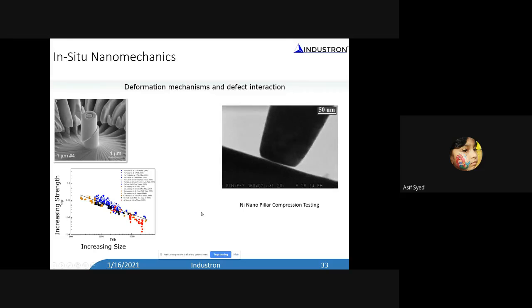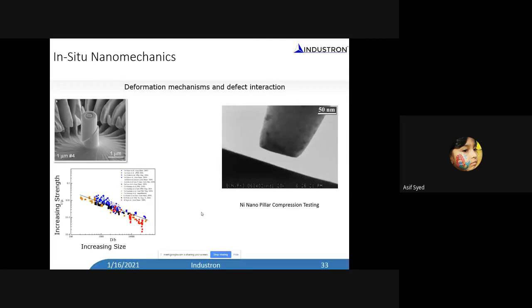Now we compress it, and you can see a marvelous thing happen. When you compress, all the dislocations that were there in the pillar disappear, and the pillar becomes totally dislocation free. This is something against what we talk about with annealing and work hardening. For example, in mechanical deformation, if there are dislocations, when you apply a stress, it should create more dislocations. But in this case, all the dislocations were moving to the surface and disappearing at the surface, and that makes the pillar dislocation free. As you know, when the material is dislocation free, it will almost go to the theoretical strength of the material. That's why the strength increases.